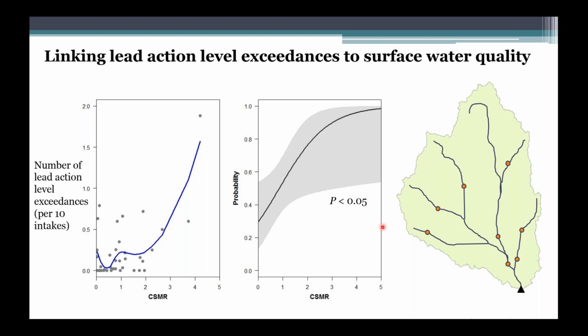So instead, we used a logistic regression to ask about the probability of there being at least 1 action level exceedance per 10 drinking water intakes in the basin. The data have a lot of scatter, but we did find a statistically significant relationship such that places that had higher chloride to sulfate mass ratio did have a higher probability of having a lead action level exceedance. Okay, there is a lot of uncertainty around this relationship, and that's really to be expected because we didn't do anything in terms of looking at the size of the water distribution systems or looking at the kinds of corrosion control that was in place in these. And I guess strongly advocate that is some follow-up work that needs to happen.